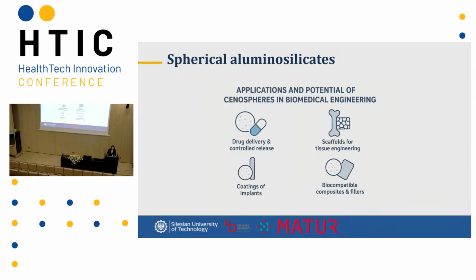But today we talk about biomedical engineering. That kind of filler can be used in different kinds of materials, from scaffolds for tissue engineering, then biocompatible composites and fillers, coating of implants or creating implants when we talk about combination with a metallic matrix, and also drug delivery. But if we want to mix it with some kind of matrix, for example a polymer matrix, because it is so much easier than the metallic matrix, it is very difficult, because that kind of material, its shape and surface, is very smooth. So we must change the surface to have a good bond with the matrix.